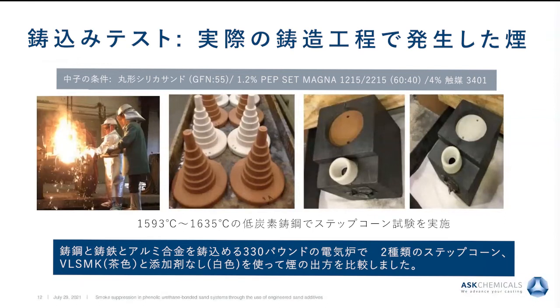for the smoke reduction. You can see there the step cones made, the darker ones are made with the additive. The light color is the one with no additive. And we place them inside graphite molds. The idea with the graphite mold is that we only see the contribution coming from the core in case we want to determine the smoke and emissions. So we want everything from the core, not the mold. At the moment we were going to make these videos for recording this event, we removed those pouring cups. They get removed immediately since they're also made of PEP SET. So we removed them. Let me show you now a video that we made.